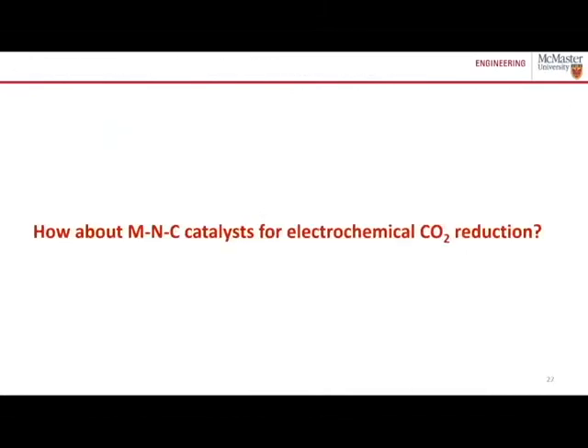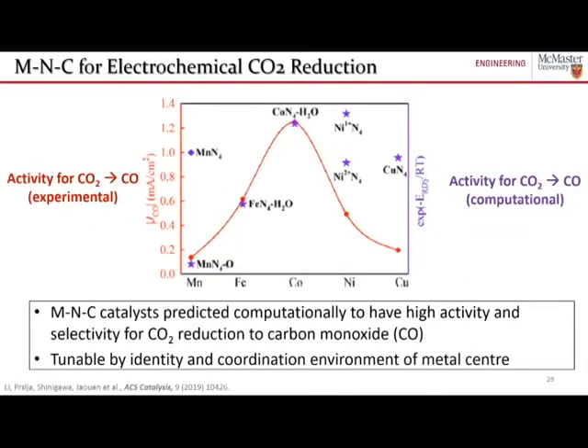So how about the development of these metal nitrogen carbon catalysts for electrochemical CO2 reduction? Now, there's been a little bit of work done in the past few years on this topic. Particularly, I want to highlight a very nice paper that is both computational and experimental. You can see in red, all the data points in red are experimentally measured activities for the conversion of CO2 to carbon monoxide on these metal nitrogen carbon catalysts with different metal center types. So there's manganese, iron, cobalt, nickel, and copper. And you can see cobalt is the most active that they tested using their preparation processes.